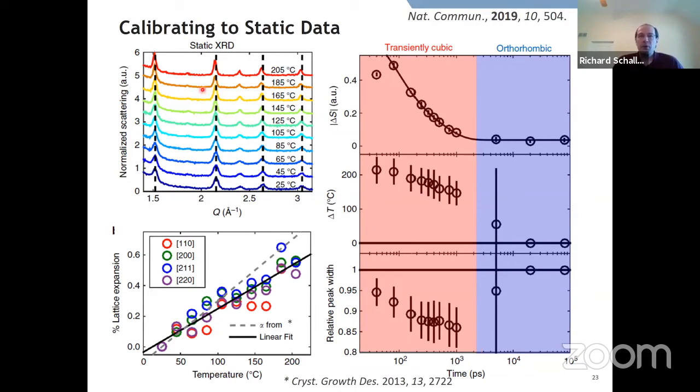Okay. And from knowing the changes in X-ray diffraction peaks of especially the octahedral types of features, this is something where we can start to read out what's an effective lattice temperature, because our derivatives relate ultimately to the shifting of these diffraction peaks.